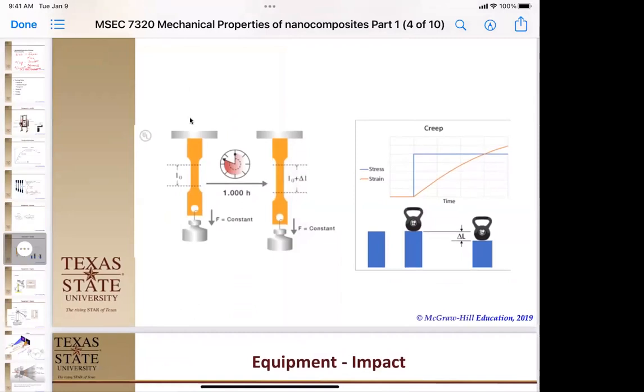It depends on the ASTM standard you want to do, but there's usually some constant weight, some constant temperature. You can actually do this at 3 different temperatures and look for a superposition curve where you're just looking for that distance change. Notice it's not the total distance change, it's the distance changed in that cross-sectional area you want to measure. When you neck down those dog bones, that cross-sectional area in the neck down region is the one you're measuring your strain unit area on. So you'll see that again.